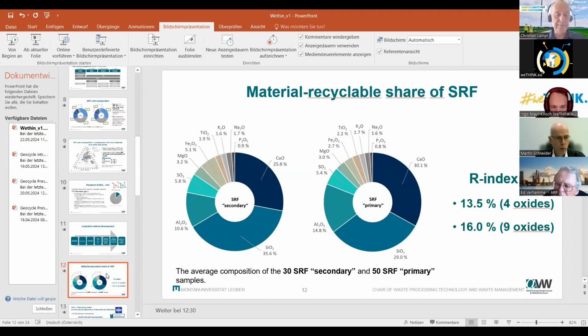The result of this analysis, I mentioned before, was a database of 30 and 50 samples. The result is that the recycling content of 1 ton of waste, which we are using for the co-processing, is on average 13.5%. So 13.5% of 1 ton of waste is material recycling, if you consider just the 4 main oxides.